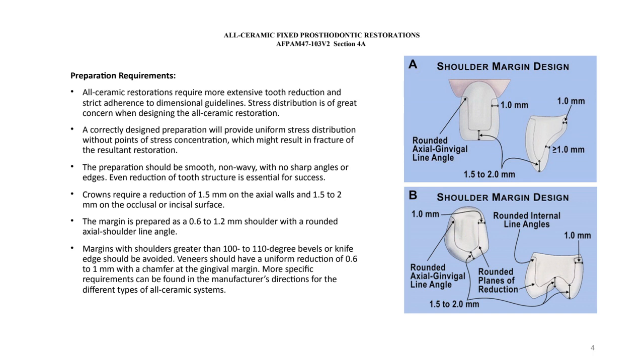This requirement ensures the final restoration inserted in the patient's mouth is long-lasting. If the restoration thickness is lower than the required 1.5 to 2 mm, the restoration might break when the patient bites down hard. These are the specifications manufacturers recommend when developing dental materials — to ensure there is enough clearance from the mesial, distal, and occlusal contacts so the restoration can withstand the patient's bite force.